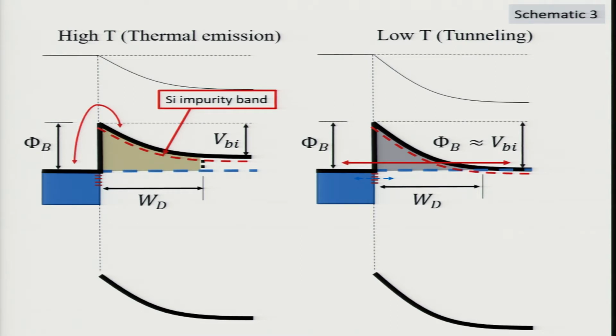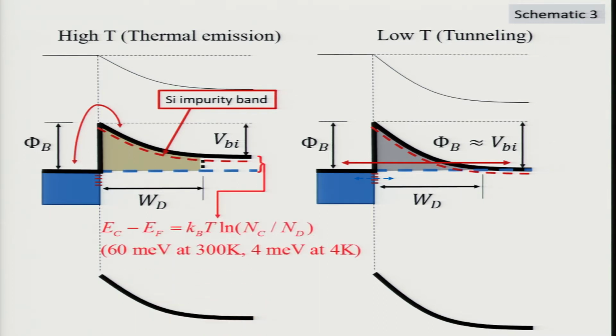So we can do low temperature experiments here. And when you lower the temperature, notice what happens: this distance here, which is the difference between the conduction band edge and the Fermi energy, decreases. It's 60 millielectron-volts at room temperature, but it goes down to 4 at 4 Kelvin, and you can get into a tunneling regime. So in some sense, we can go to low temperatures because we don't have freeze out. You can have over-the-barrier processes. As you lower the temperature, you have thermal field emission, and then you could have pure tunneling with maybe some thermal effects because you still have temperature in the problem.